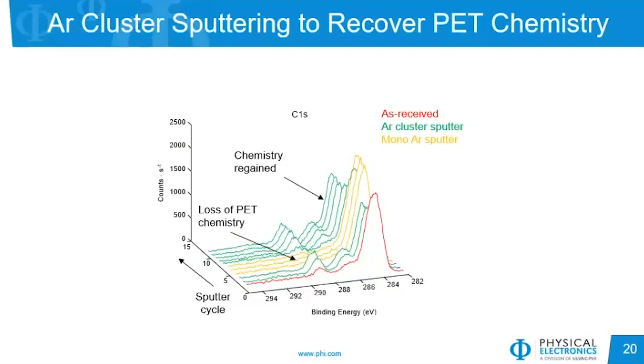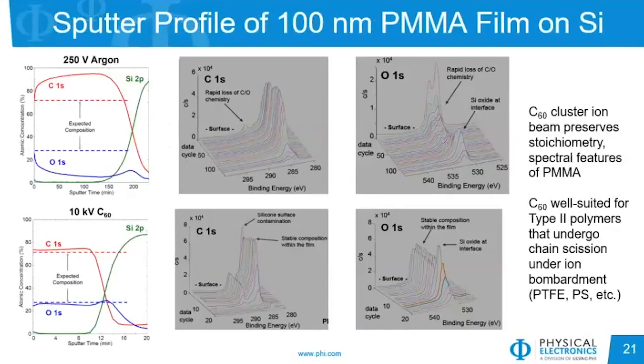In another example of PMMA, we can show how monoatomic argon just does not do very well with cleaning of polymer materials. Even at a low energy at 250 volts, as soon as we start sputtering, the oxygen concentration decreases, our carbon increases, far away from our expected composition for PMMA. Looking at the C1s spectrum in the top middle plot, we can see at the surface, which is toward the back of the figure, we quickly lose our spectral features once sputtering with argon. However, with a C60 ion gun, we maintain the composition and we also maintain the spectral shapes for the PMMA.